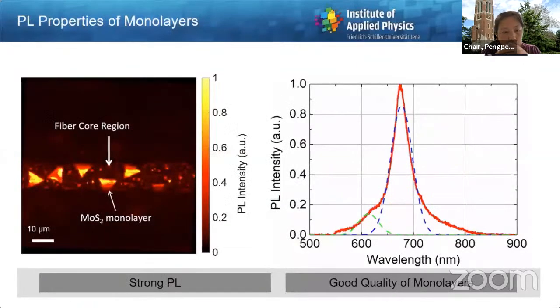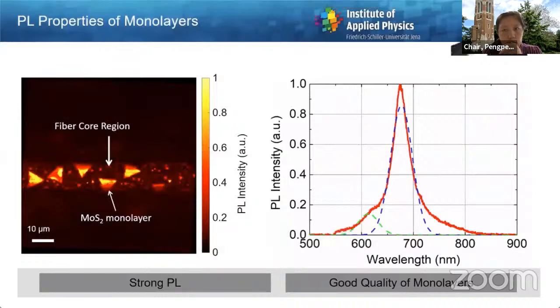And as a next step, we'll also look into the electronic properties. To better understand that, we measure the photoluminescence and compare it with the photoluminescence from crystals which are grown on planar substrates. So the photoluminescence map, again, this is our optical fiber. Optical fibers are basically placed in this direction. You look at it from the side, you make a photoluminescence map of the core region, and you see these nice monolayer crystals here.